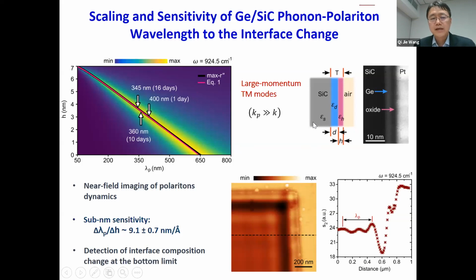Because when we look at such a system, to accurately describe it, we also need to consider the oxide layer of germanium, because germanium can be oxidized in the ambient environment. So therefore, in principle, we should consider a 4-layer structure. However, this system analysis is similar to what I have described in the MoS2 silicon carbide structure. And it also follows that we do the calculation of the dispersion curve. And we measure the Phonon-Polariton wavelengths as a function of the thickness of the oxide layer, as a function of time, okay?